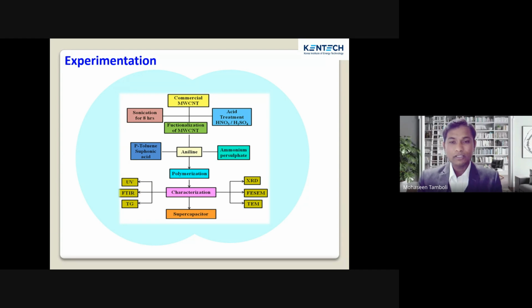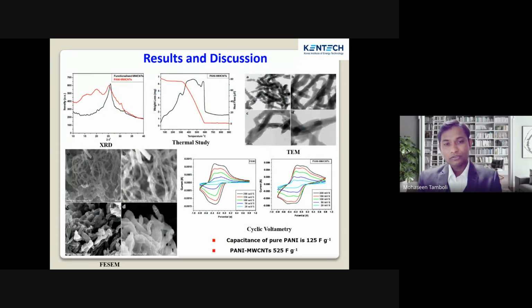Generally, polyaniline is a promising, very cost-effective, and stable conducting polymer compared to other conducting polymers, and we used MWCNT and polyaniline for supercapacitor application. When we check the XRD results, the red color shows polyaniline and carbon nanotube. No carbon peak is observed in the XRD of polyaniline and carbon nanotube, because of the overlapping of the carbon peak with the main peak at 25 degrees, as you can see here.